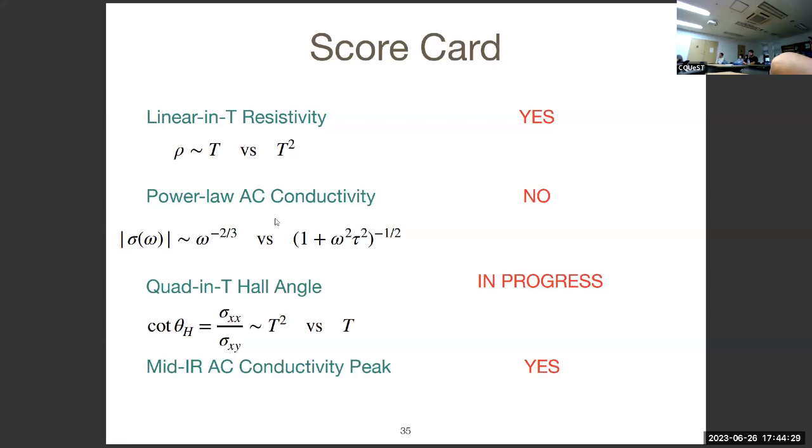If you make one assumption, which is that the phonons have a dispersion relation which is not linear. They usually have omega equals k. That is kind of part of the definition of a phonon. If it's not that, you would hardly call it a phonon. But suppose there were some other degree of freedom in these solids that somehow has a dispersion relation that goes like omega equals k squared, or omega equals k, whatever it is, and also interacts with the electron in a fairly similar manner, like a Yukawa type interaction, then you can show that you can get linear resistivity.